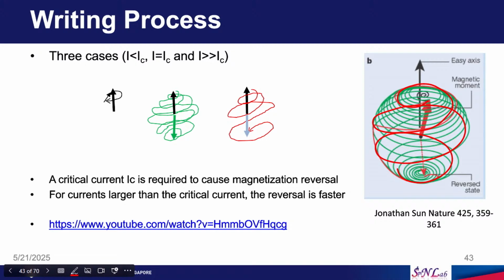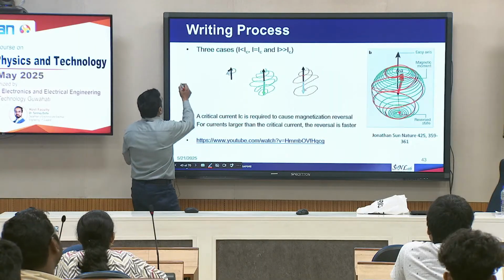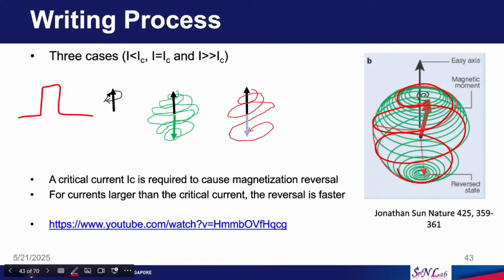Okay. So, if you apply current for a short time, let us say you apply a current pulse with a certain pulse width. If this current amplitude is lower than what is required, maybe your spin will precess for some time, then finally settle in the same direction. So, switching will not happen. Only when this amplitude meets the critical current, we can achieve reversal.